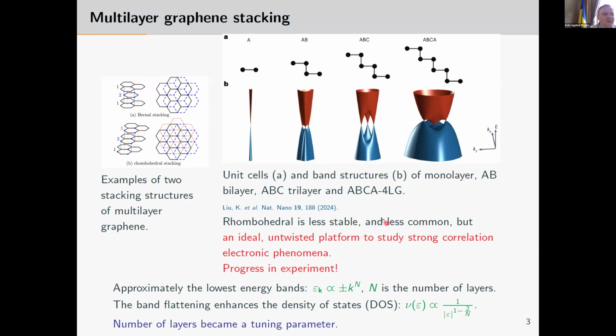But still, it turned out that it's much simpler and easier as an experimental and also theoretical platform as compared to the twisted graphene, which you heard about. And about the progress in the experiment in recent years: for monolayer graphene, it was possible to observe it in an optical microscope and then do work. Here, more sophisticated experimental methods are necessary to recognize where we have this rhombohedral graphene. And then it's encapsulated in boron nitride, and a huge experimental work is done.